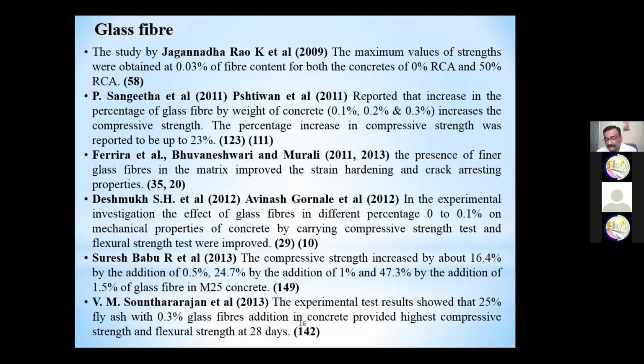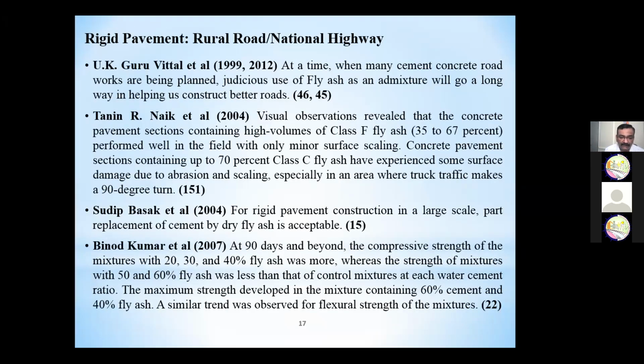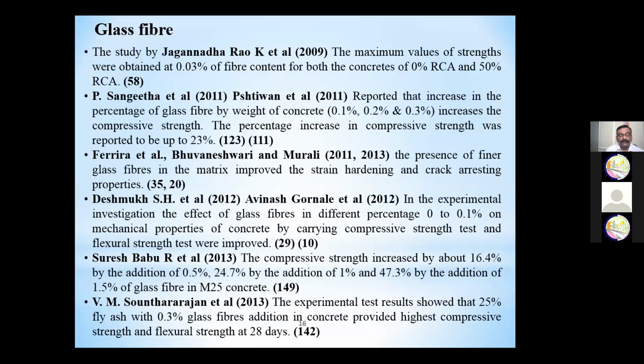Now, some research is based on glass fiber. They used 1%, 2%, 0.1%, 0.2%, 0.3%, depending on the weight of concrete. Some refer to the weight of the cement, and somewhere they refer to the total quantity. They added different percentages of the glass fiber. And the glass fiber increases the tensile strength, so it is beneficial from the flexural strength point of view. It is beneficial to the rigid pavement. Based on the research, we find 0.1 to 0.5% is good regarding the fibrous percentage.